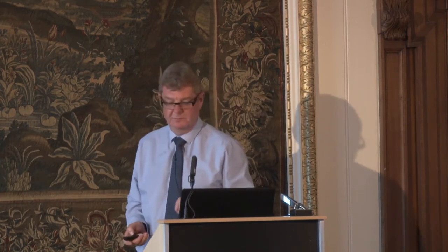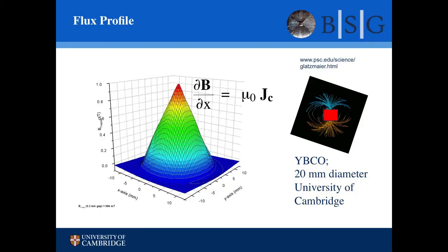So we need to pin these magnetic flux lines. We need to put something in the material that stops these field lines moving. And if you get it right, then you can produce a material that traps, because you force the field in and it can't escape, it's trapped in there. If you get the flux pinning right, you get this beautiful, we call it a Bean cone. So this is a magnetic field distribution of a superconducting sample, and this one's showing a peak field of about 1 tesla. But you see this beautiful flux cross-sectional area.